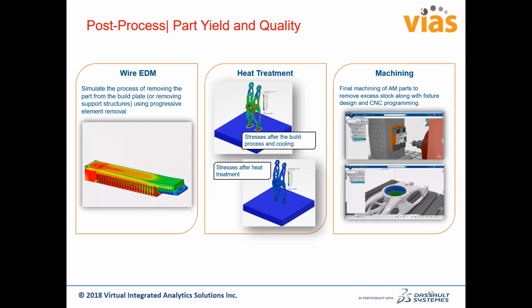Sometimes additive manufacturing parts will have voids, and to reduce the voids there is high pressure heat treatment. Also sometimes you want to reduce the residual stresses, so you heat treat your component. As part of post-processing, you can take that manufactured part and get those other post-manufacturing effects. This will give you an idea of what happens when you go from printing to actually putting that component in a real-life environment. You can simulate the entire process.